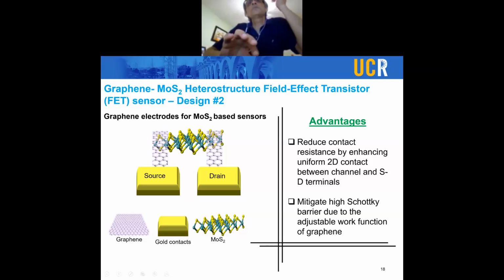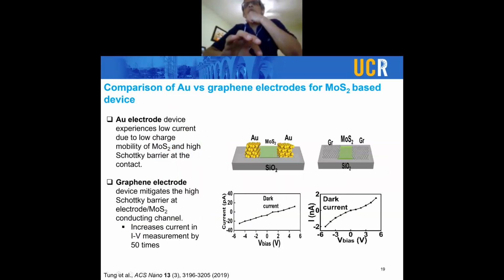So why not just use a 2D junction, 2D material of MoS2, 2D material of graphene, and create contact electrodes made out of graphene, and then see what type of benefits we get by creating this type of design in which our MoS2 is going to be bridging the gap between the graphene electrodes. And these source and drain electrodes are basically graphene electrodes that are now with the contact pads, to mitigate the Schottky barrier due to the adjustable work function of graphene. And as our first test to show that there is a benefit of putting graphene as the source and drain electrode versus the gold electrodes,